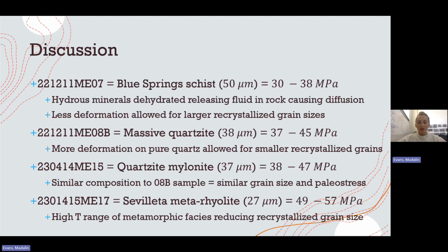This had a flow stress between 37 to 45 megapascals. And the idea for this one is that more deformation on these pure quartz allowed for smaller recrystallized grain sizes. The 15 sample, which was the quartzite mylonite sample, had a mean recrystallized grain size of 37 microns and had a flow stress range between 38 to 47 megapascals.